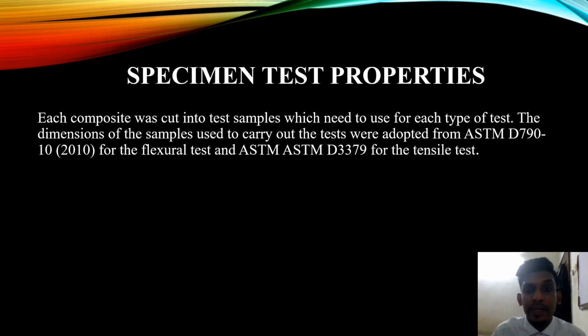Now, the specimen test for the properties. Each composite was cut into test samples which are used for each type of test. The dimensions of the samples used to carry out the tests were adopted from ASTM D790-10 for the flexural test and ASTM D3379 for the tensile test. The entire test was carried out for untreated and alkali treated sugar palm fiber reinforced composite.